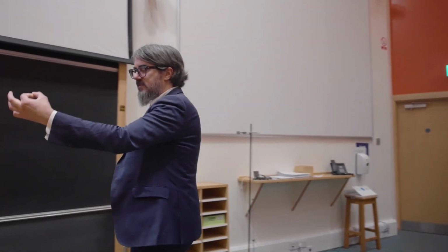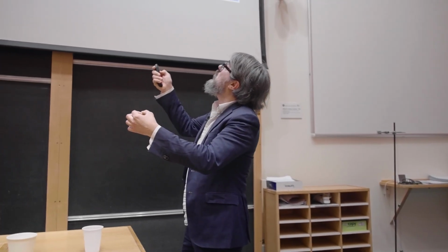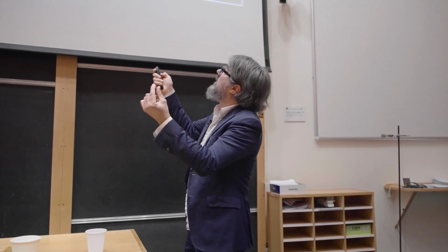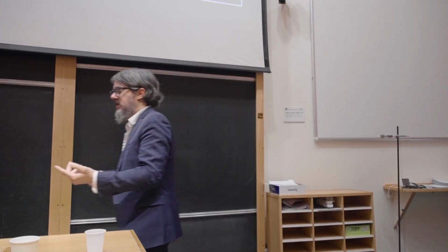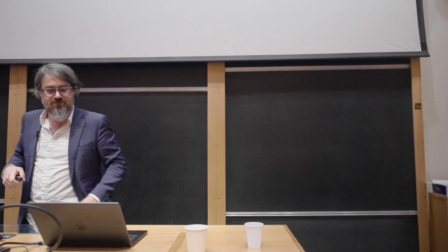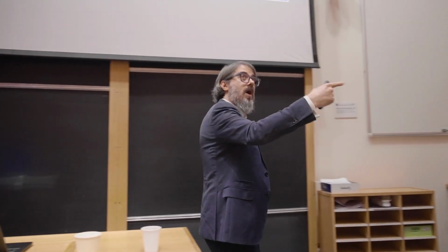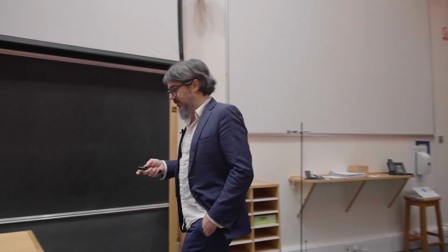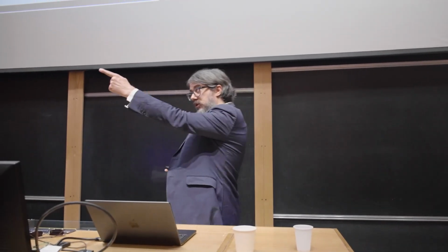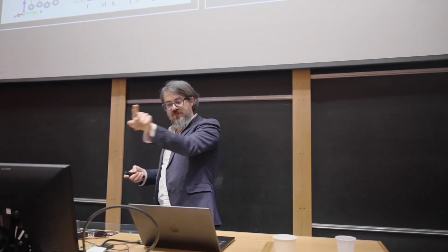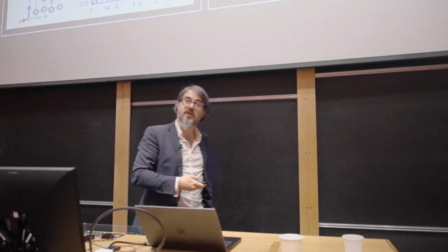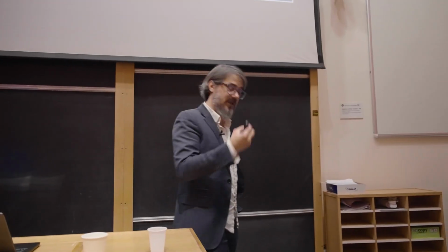And the fact that it has a vortex is very easily seen, because if I would move down here to the Dirac point, then you can immediately see that you'd have a singularity. And this vortex is basically the fact that the wave function winds as the momentum winds around the Fermi surface. The wave function also winds in a way that's not zero. So the wave function is not just a vector that's always zero, it follows the momentum in this case. And that's the fundamental property of this Dirac node. It's a topological invariant of this metal in this case.